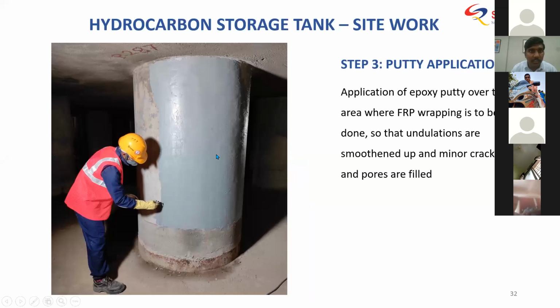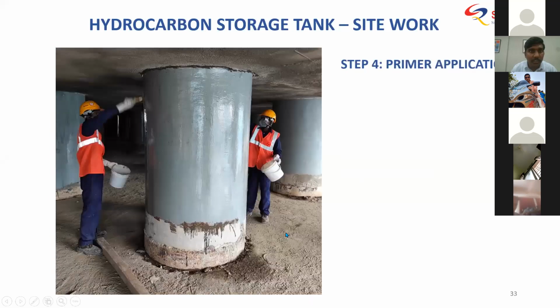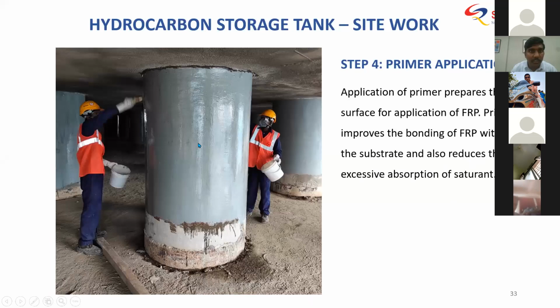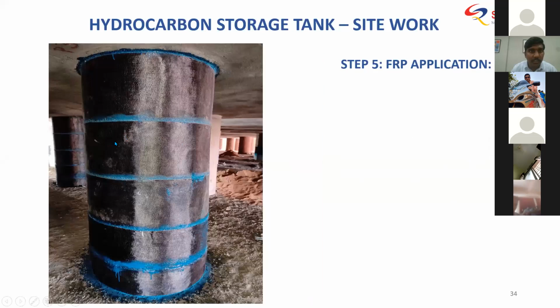So after this, you apply the primer so that the excessive consumption of saturant will not take place. Then you do the carbon fiber wrapping. The blue color that you see is the saturant of the FRP, and the black is the carbon fiber FRP itself. These lines that you see in the vertical direction are because of the cross stitching, and the fibers are actually oriented along this direction, the red line that you see. So basically 4 layers as per design were applied.